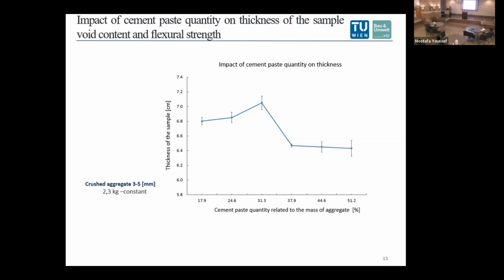By the way, I conducted some experiments at a company, and when we tested, the results for mechanical properties were 30 to 40% lower than in the lab. This is the impact of the compaction and vibration energy. So it's quite a crucial step. Maybe using some fine particles of the sand may help.